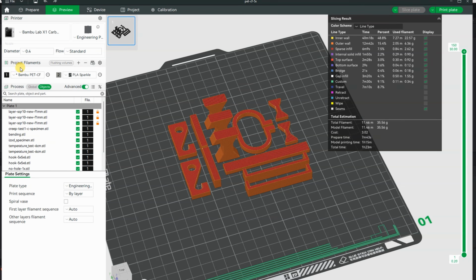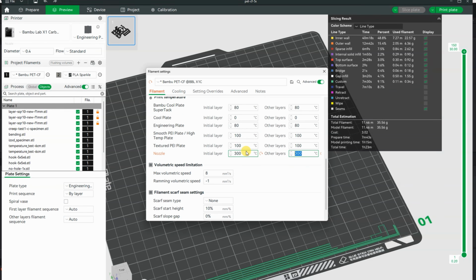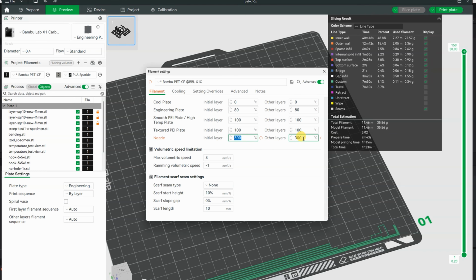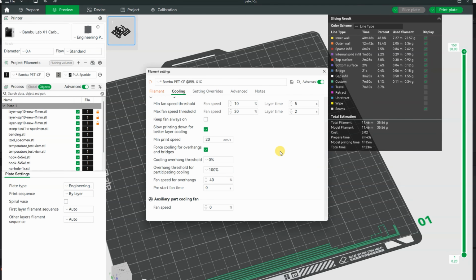And these 2 are for the tensile test. And I'm using the BambuLab PET CF profile for every printing, and only one thing I changed, and that's the nozzle temperature to 300 degrees Celsius. And I will use the same settings for all 5 filaments.